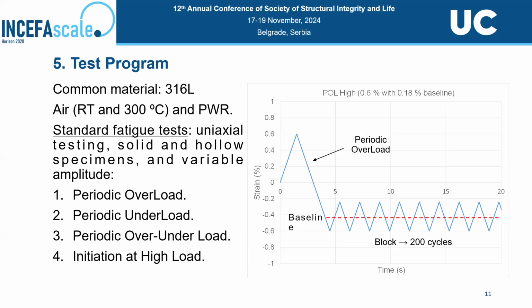To cover this topic, we perform this kind of test with different variable amplitude. So in this case, this example is for a periodic overload, and we use this common material in PWR. The test was performed at room temperature and 300 degrees in PWR environment. We perform this following the protocol I mentioned and the standard fatigue tests, and we have periodic overload, underload, over and underload, and high load interactions.